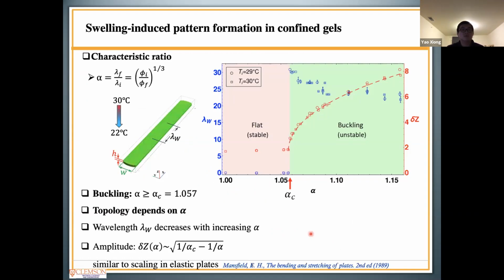In our first scenario, the temperatures of confined gels are quenched down to various values. Here is one example of the development of pattern formation. In this image, we plotted the wavelength and the amplitude of fully developed patterns from our simulations. Each point represents one independent simulation run. We tried two initial temperatures and find samples with the same initial size and cross-link density would have similar patterns at a given alpha. And we can observe buckling if the alpha is larger than the critical value alpha c here.